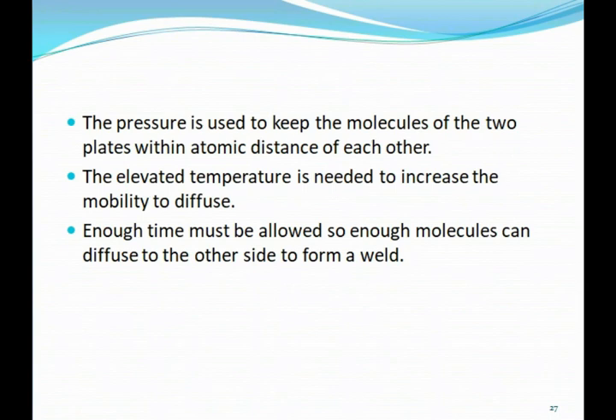Solid-state welds, formed without melting the base materials, are achieved by applying pressure, and sometimes heat, over time, allowing atomic bonding to occur across the interface. The pressure is used to keep the molecules of the two plates within atomic distance of each other. The elevated temperature is needed to increase the mobility to diffuse. Enough time must be allowed so enough molecules can diffuse to the other side to form a weld.